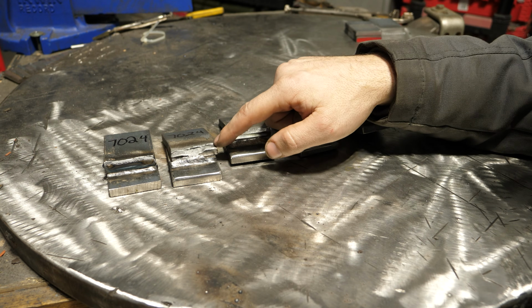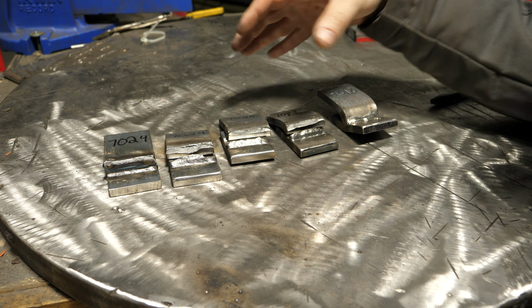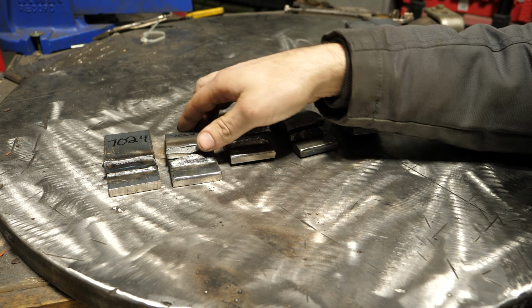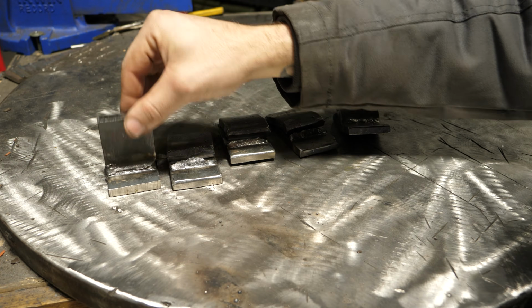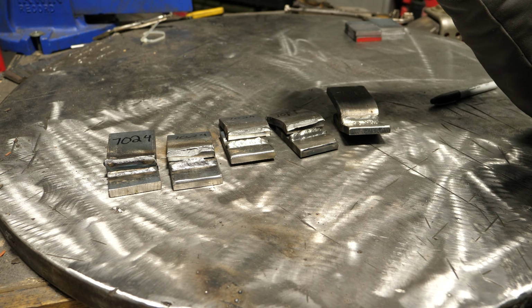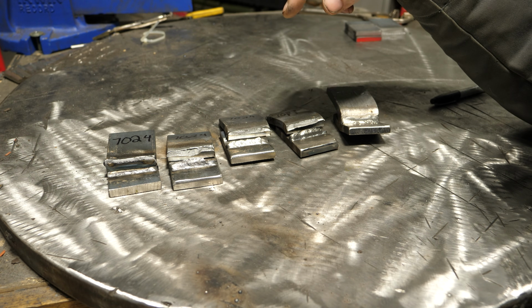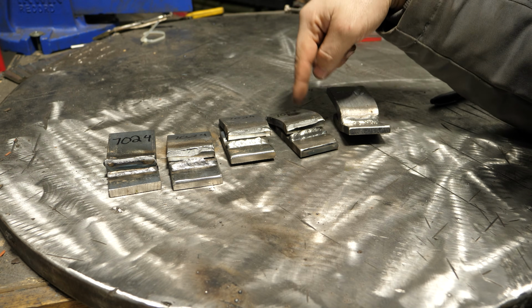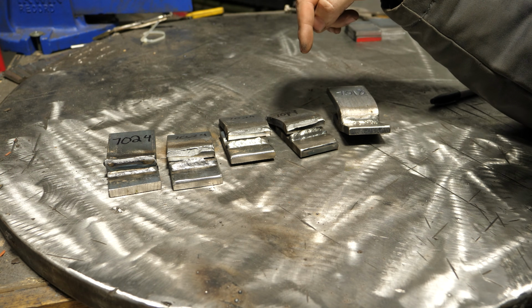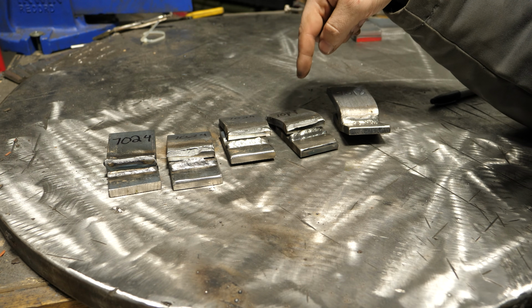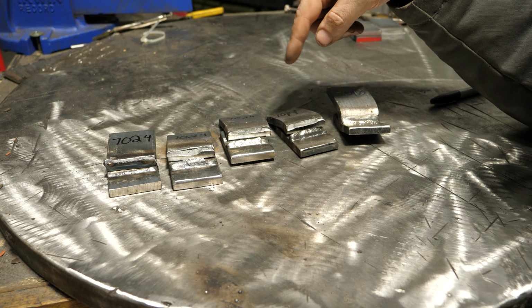Now, the one thing I do like about the 70-24 is that on a bend towards the face, this guy right here, it broke at close to, I would say, in the ballpark of 70-18. So that's really good. It seems to have more penetration than 70-14 does, and that coincides with past testing I've done on flat plate, and even fillet welds, that showed 70-14 tends to have the least amount of penetration of all the rods I've tested, along with 60-13.